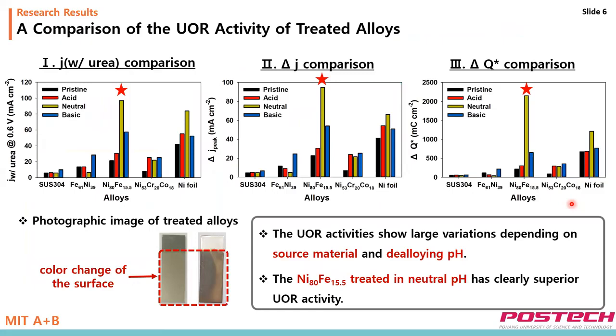So this slide shows the result of UOR performance. First of all, this photograph can be simple evidence that surface transition occurred by changing the surface color after potentiostatic de-alloying methods under 3 types of pH condition. Actually, as shown in the graph, UOR activity was evaluated with 3 parameters. Here the UOR activities show large variation depending on source material and de-alloying pH. Using the 3 indicators, each result shows that the Ni80Fe15.5 alloy treated in neutral pH has the highest UOR activity.